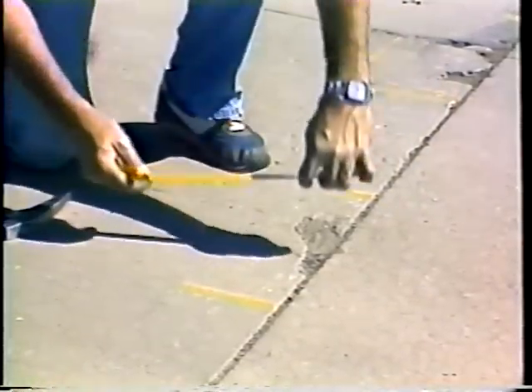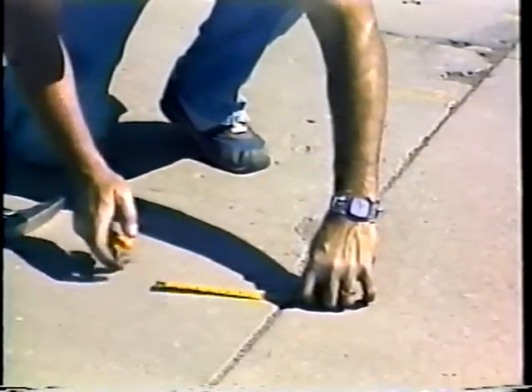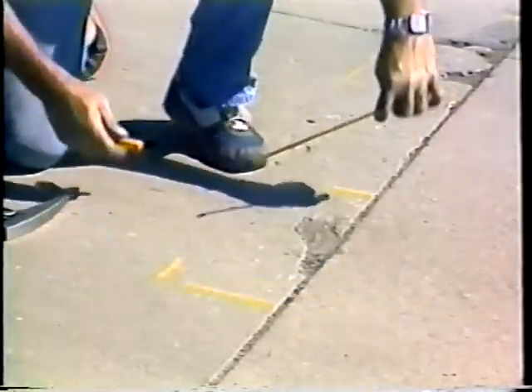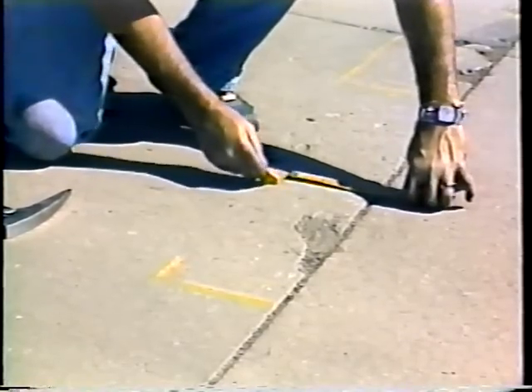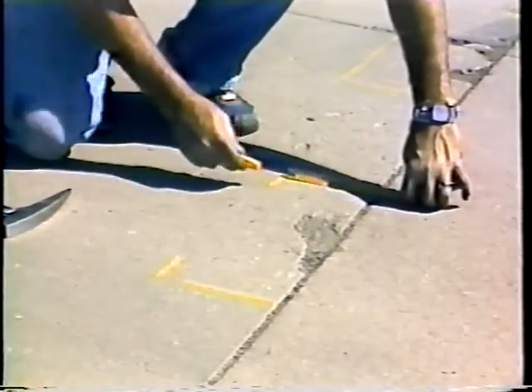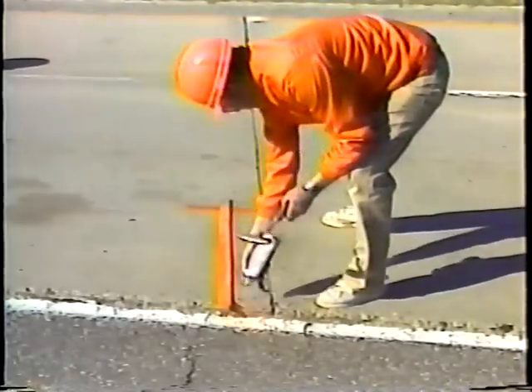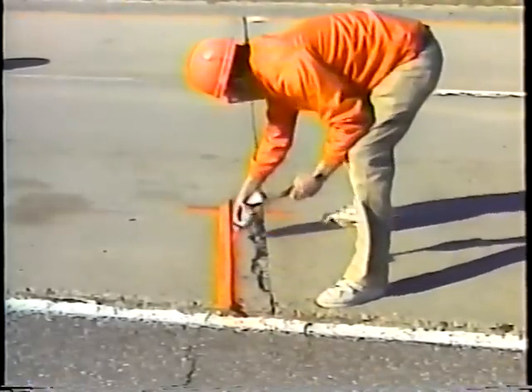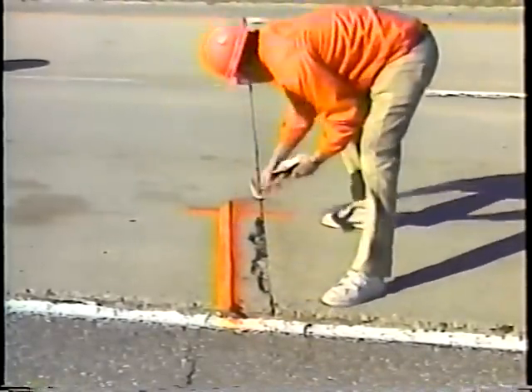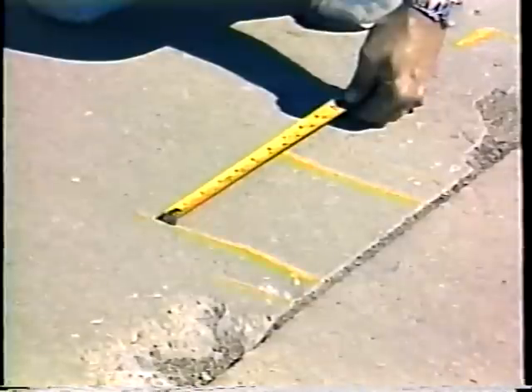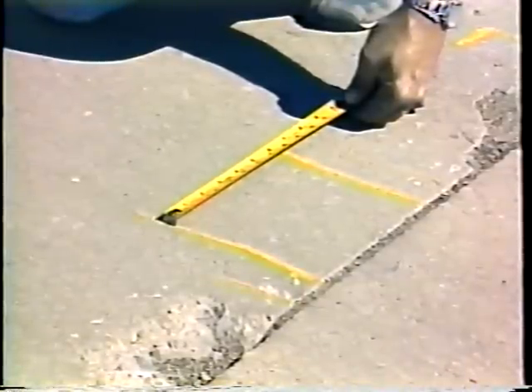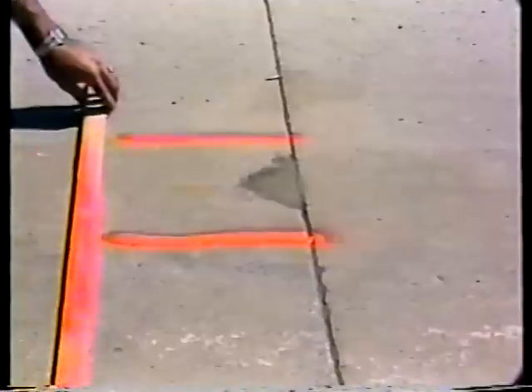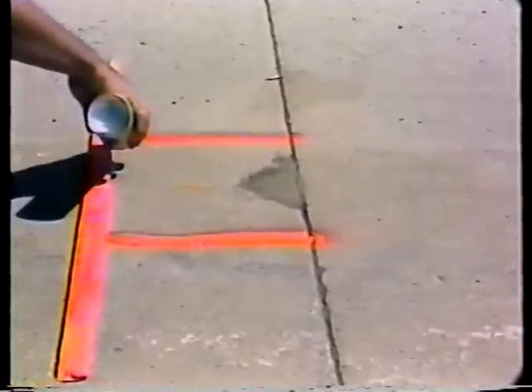Normally, the marked area should extend 4 inches beyond the distress to ensure that all deteriorated concrete will be removed. If the marked area will extend within 1 foot of the shoulder, the repair should be extended to the shoulder. Similarly, if two repairs will be within 2 feet of each other, they should be marked as one repair. In all cases, the repair should be marked in a square or rectangular shape.